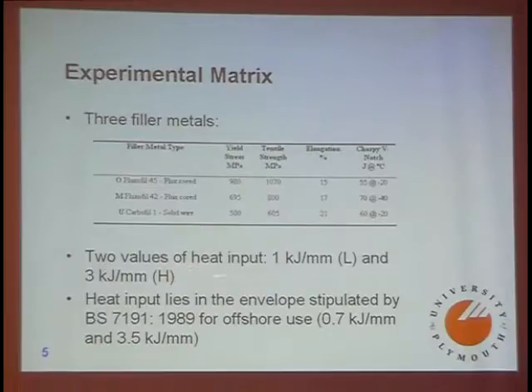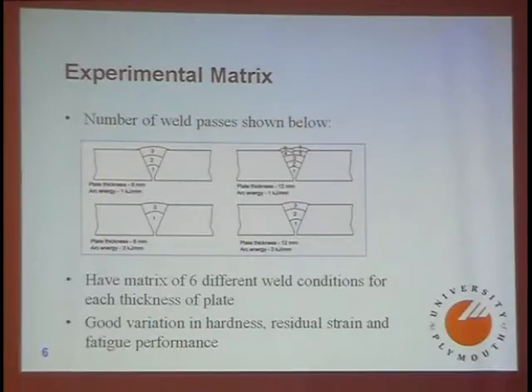We use 2 values of heat input, and those lie within the envelope stipulated by a British standard for offshore use. And so I've got a fairly broad experimental matrix to try, which should in principle give quite variable micro-hardness and residual strain grade, and does. And so if you found a reasonable correlation across that broad range of data, you might think that you were on the right track. So when they made the welds, this is what they did.